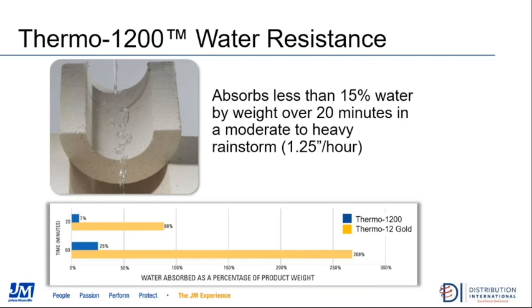So we've made it water resistant so it'll withstand a moderate rainstorm for up to 20 minutes and absorb less than 15% water, where prior to making it water resistant, it would absorb 88% water, which is what that first bar chart shows. This was a really significant advantage, and it was designed for the contractors, but what we found is the engineers like it way more than I thought, and they're actually specifying water resistant Thermo-1200.